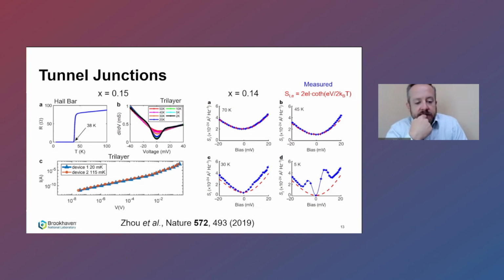The important thing, though, in panel C, is that there's definitely no supercurrent over several orders of current and voltage range at the lowest temperatures, or any temperature really. So these junctions clearly don't have any kind of Josephson coupling from one side to the other, but they are useful for tunneling experiments. The group at Rice looked specifically at the noise level coming from these tunnel junctions, and that's shown in these right panels. Here, in A, B, C, D, we see the noise spectra taken at different temperatures, and the red dashed line is a plot of the expected noise level.